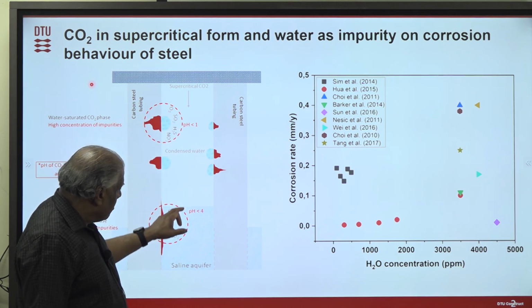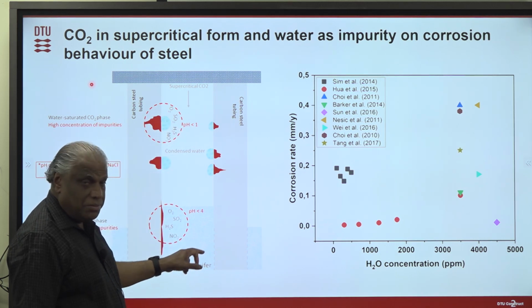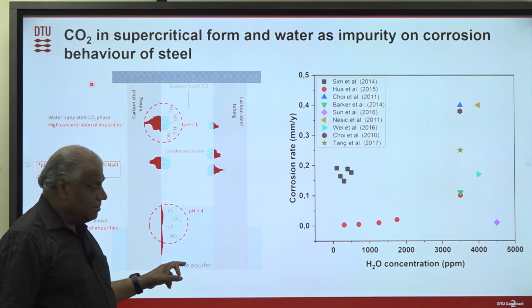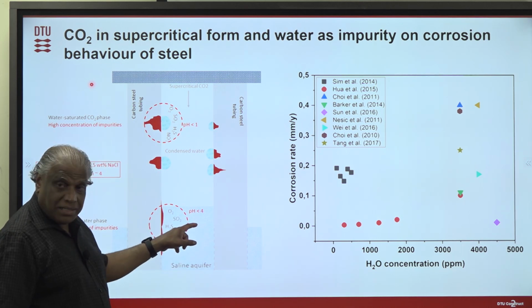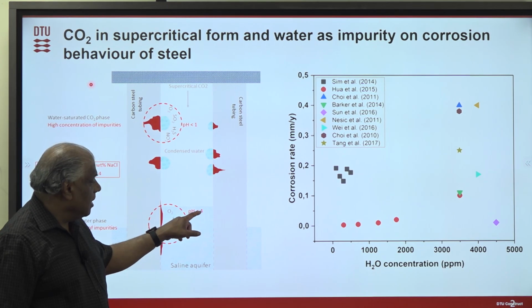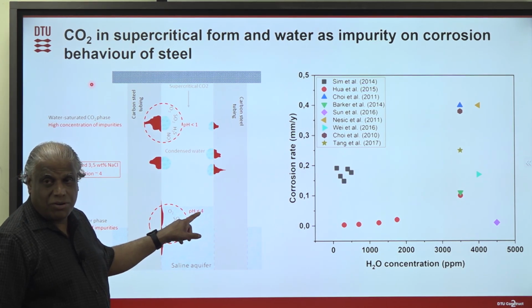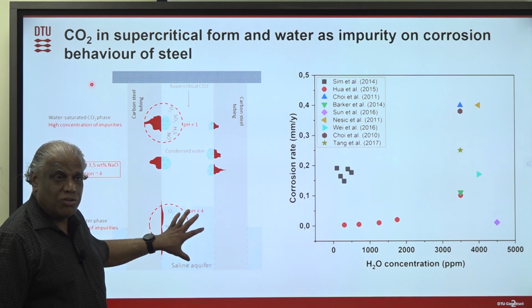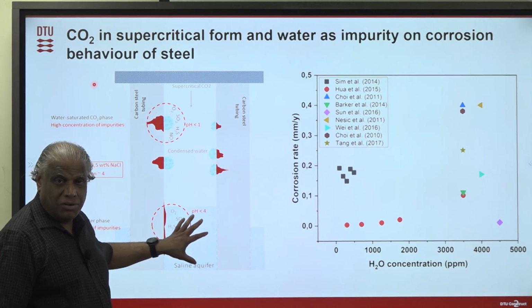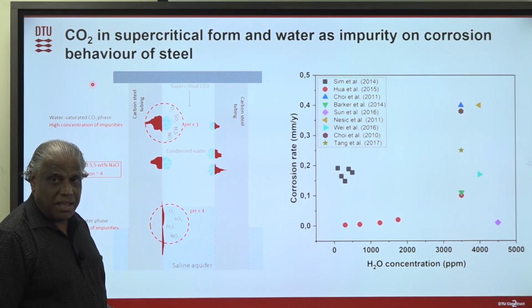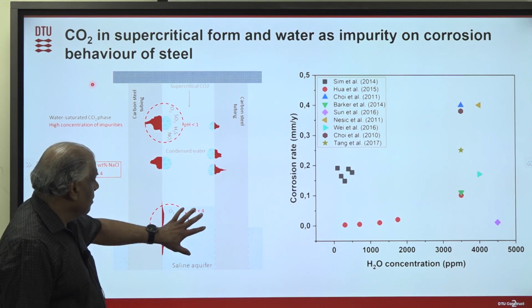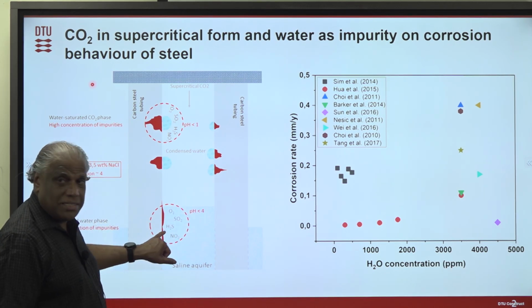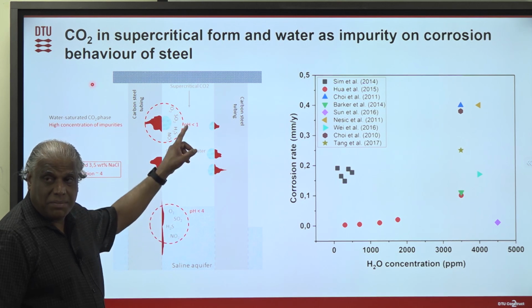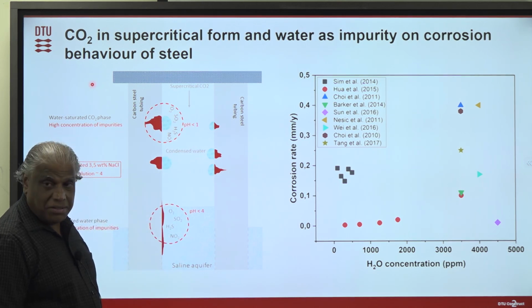Then the CO2 comes down into the reservoir. CO2 is dissolved in the water like carbonic acid. Then you have a pH of 4 or lower. So this is like normal oil and gas corrosion, or carbonic acid corrosion. This is what happens. The only thing is that, even in this case, you also have H2S, SO2 and things like that, because that's the part coming from the carbon dioxide.